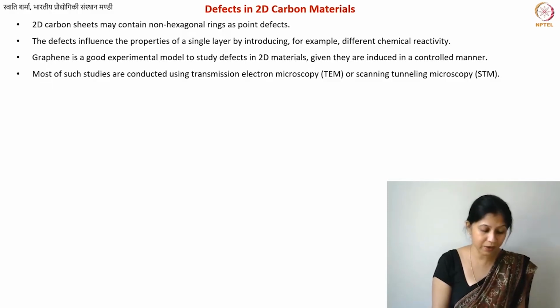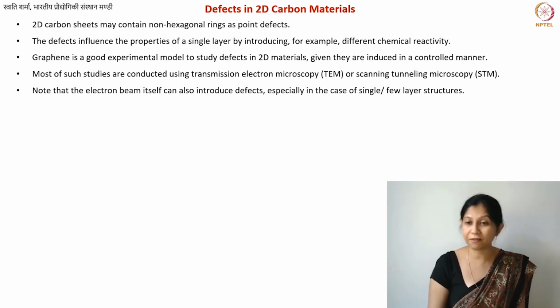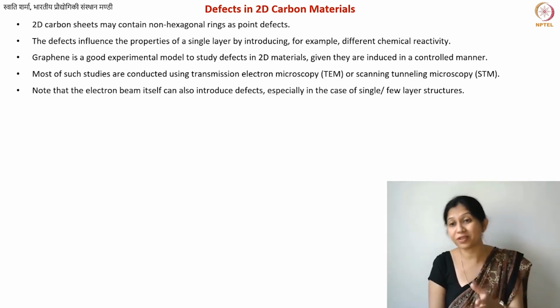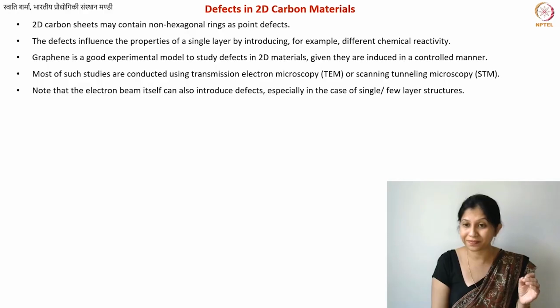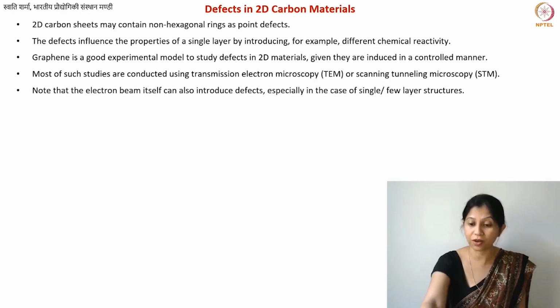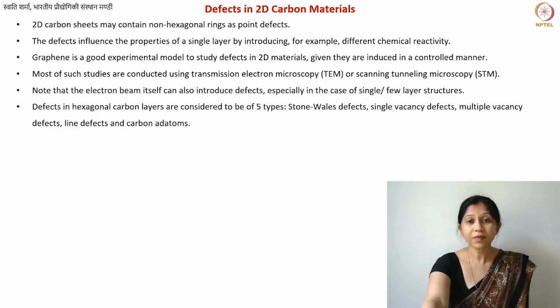One very important thing, however, is that when you're performing the TEM experiment, the beam itself can cause defects. Typically, if you're using a beam of more than 80 keV, you may end up introducing defects even while imaging your sample. So this is also something that you need to know. However, there are transmission electron microscopes that can go down to even 30 kilo electron volts. So in that case, there is a possibility that you can see such defects, or you can really get images of them.